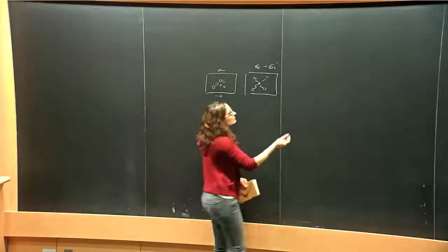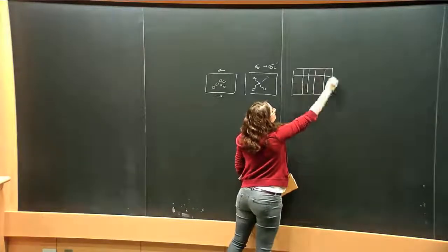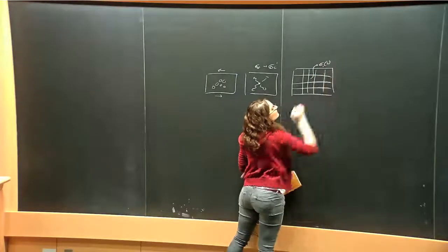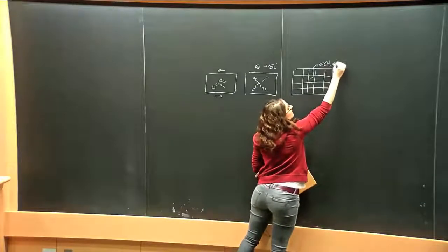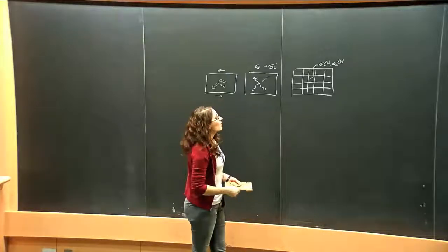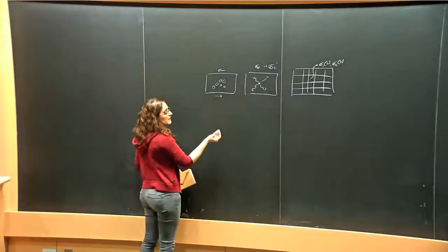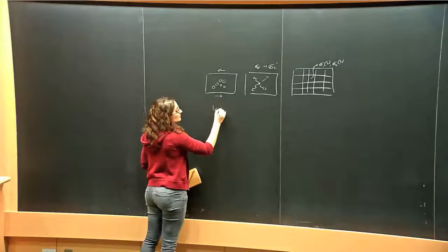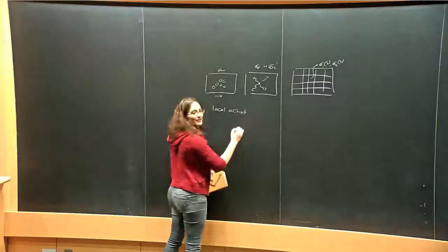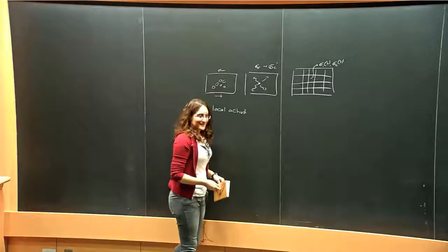That can be modeled very naturally on a lattice model, where you focus on the stress on a given site. It can depend on time. On each site, you also have a local yield stress that also depends on time, because each time you have a plastic event, you locally update the disorder. In those models, you have coupled dynamics of the local activity. You mentioned that in your talk at some point. But it would be good if you can connect this stress-based activity with the rearrangement activity.